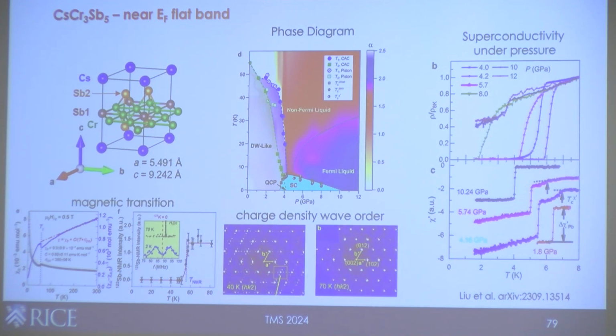It turns out this system by itself, at ambient pressure, has a symmetry breaking transition around 55 Kelvin. Experimentally, additional superlattice peaks appear that suggest a 4x1 charge density wave order that onsets across this ordering temperature. There's also evidence of a magnetic transition associated with this temperature, seen in the magnetic susceptibility here, and in the NMR shift here at the same temperature. So it suggests there are two transitions: a charge density wave order, and then an unknown magnetic transition that hasn't yet been resolved.